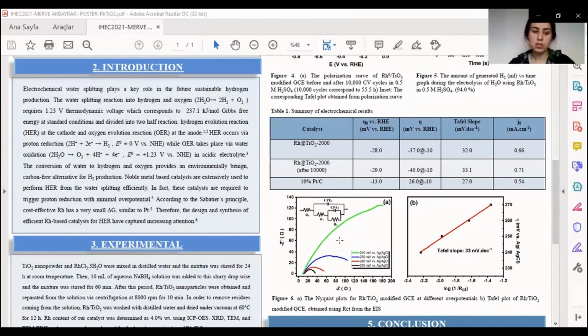The semicircles at the high frequency region are potential dependent, and their radius decreases with increasing potential, indicating faster charge transfer occurred at higher potentials. And the semicircles at the low frequency regions are potential independent and arise from the contact between the glassy carbon electrode and the metal and the electrocatalyst.